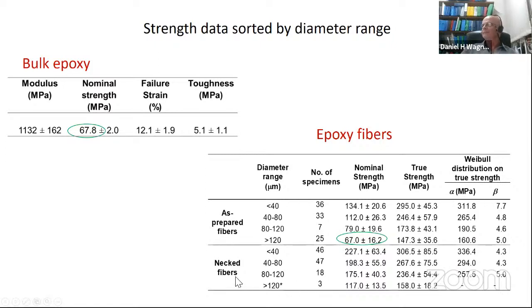If we test the necked fiber, which were in blue on the previous slide, what you get is even higher. Actually, you go up to a strength of 227 on average for necked fiber below 40 microns. So this is really a very, very large value. You can do the calculation also for true strength by dividing by the evolving cross-section, the true cross-section, and get higher values.